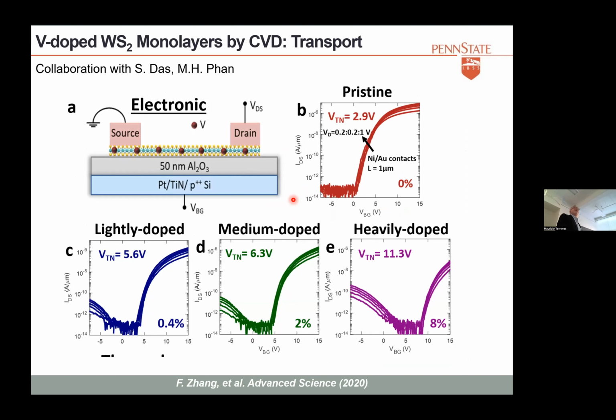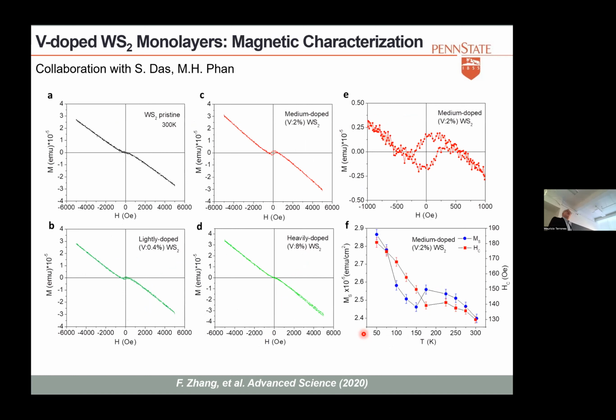We made some devices with this, and it's usually an N-type material when it's not doped. But when we start doping it with vanadium, we start to see that the P branch starts to develop, and it becomes close to an ambipolar system. Again, with different samples and different measurements that we did, we saw more or less the same trends. But what was more interesting was the magnetism here. This is something that we still need to do some more work on. I mean, this is at room temperature.